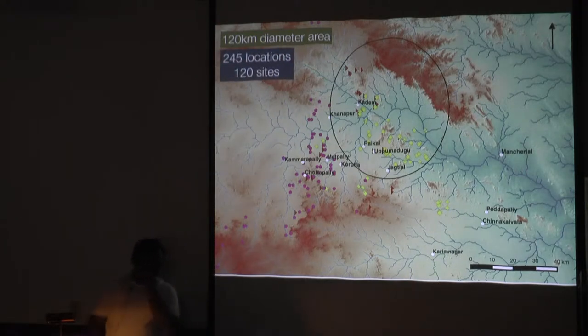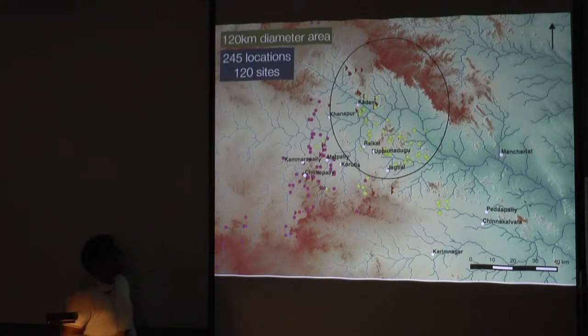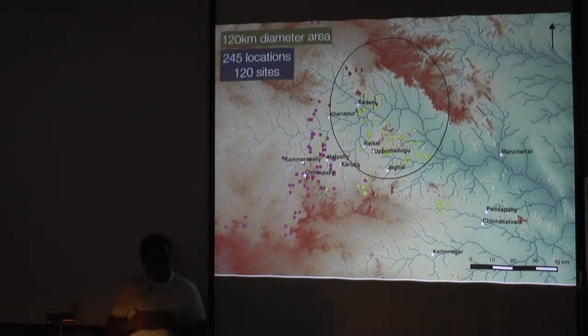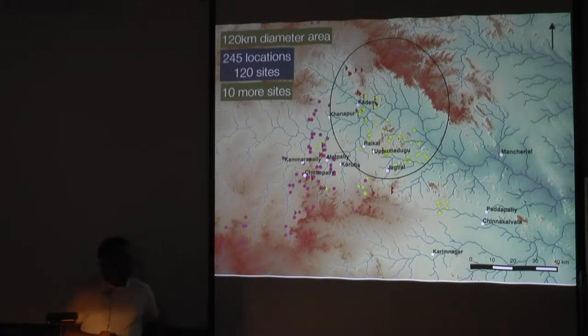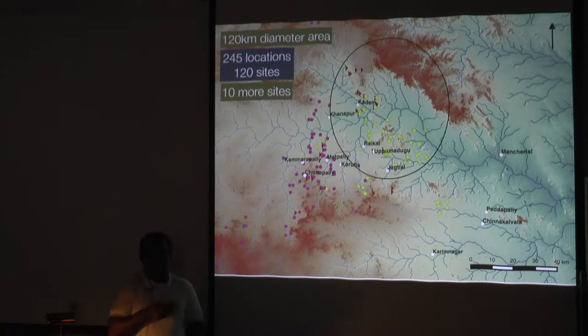So we found during the Pioneering Metallurgy Project almost 245 locations with iron smelting evidence. That includes slag heaps and some mud brick forts where slag was incorporated within the structure, and there was a slag heap nearby which was completely quarried to do that, etc. And then these were all clustered into about 120 sites. During my field work, I identified several more locations which were clustered into 10 more sites, mostly inside the forest tract.